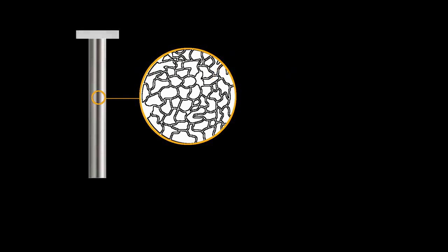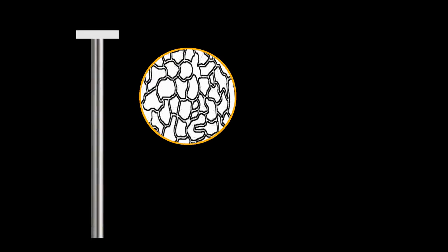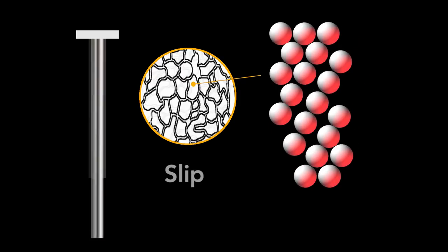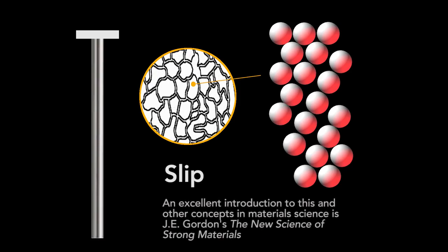If this metal rod were held at the top and stretched, then the grains might elongate. They can do this because the atoms inside move a bit. In a metal, bonds can reform more easily than in nonmetals, and so the atoms slip, although it's a bit more complicated than implied here, which looks like spherical atoms rolling along each other. It involves defects in the crystal that allow the atoms to move only small amounts. In nitinol, though, generally the atoms don't slip. They accommodate the stresses from bending, stretching, compression, and so on in a different way, which produces the memory effect.